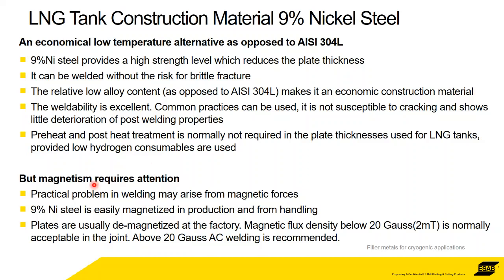One thing to watch out for — not common, but something that someone operating in this environment for the first time needs to consider — is magnetism. It can be a problem. Handling and moving these plates around creates a great risk of increasing magnetism within the base material. If it's not possible to demagnetize and there's a magnetic flux density in the steel, that can cause all kinds of problems when welding — specifically, the arc goes where it wants. We would recommend a flux density below 20 gauss. If it's above that and can't be demagnetized, then AC welding would be recommended.